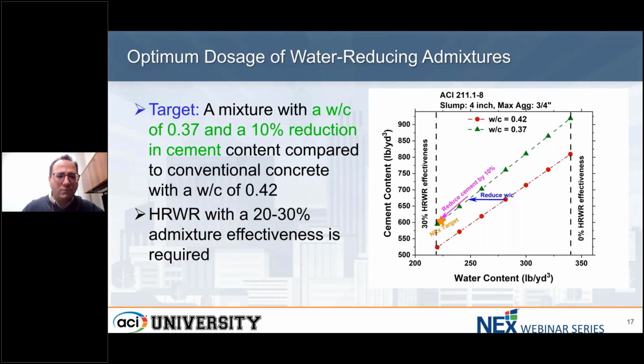So here's very basic information on the approach we took. I have this graph at the right side based on ACI 211, which is typically what we use for our mix design. I'm saying if I am targeting 4-inch slump for my mix design and the maximum aggregate size is 3/4 inches, and I'm assuming the typical water cement ratio I use for my mix design is 0.42. For that 0.42, I'm showing basically the range of water content versus the cement content I can apply, depending on that. The amount of the admixture I'm going to use to improve the workability is going to be different.